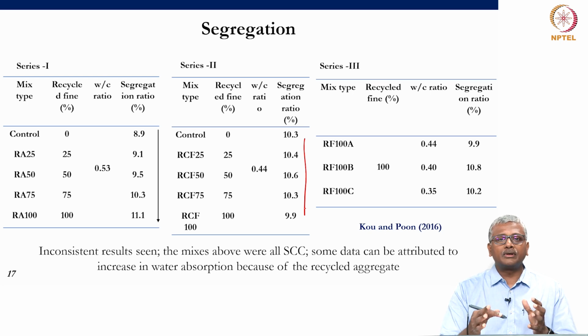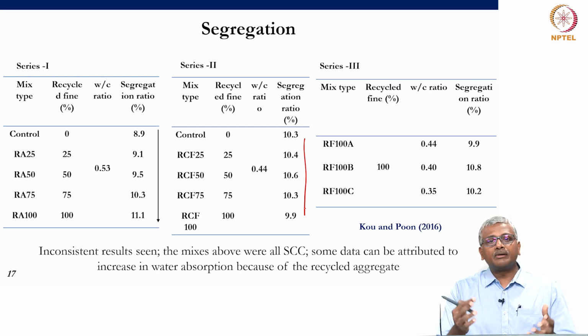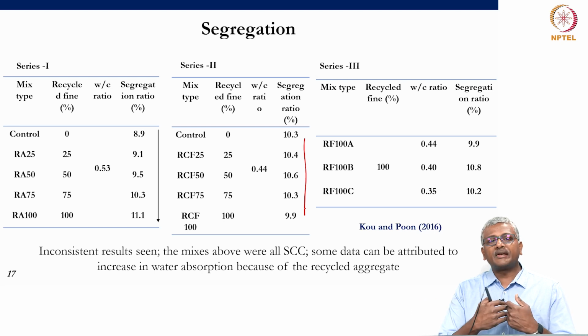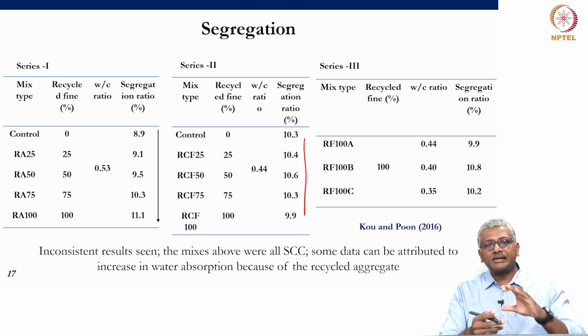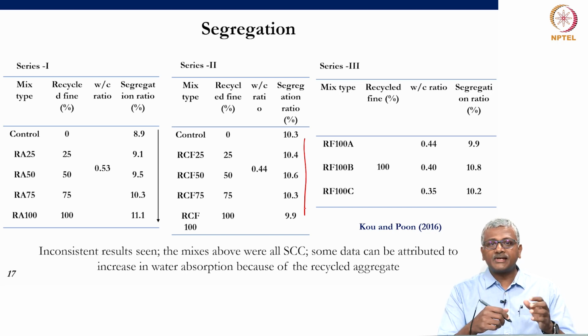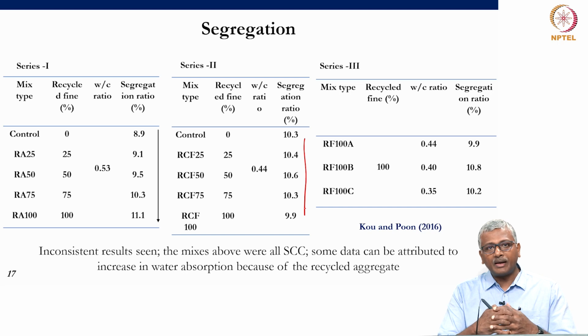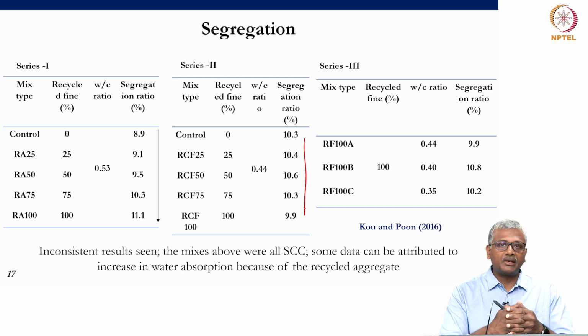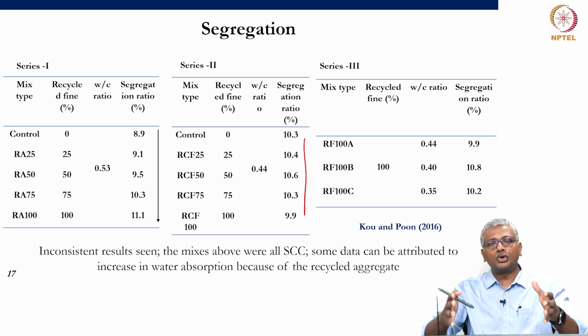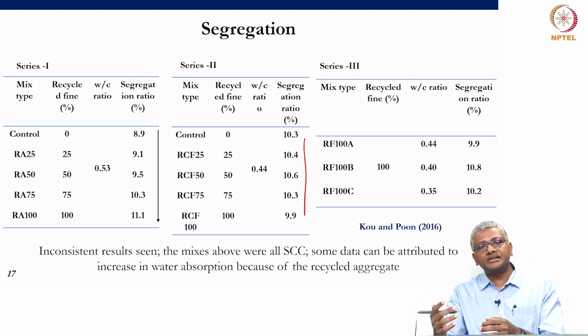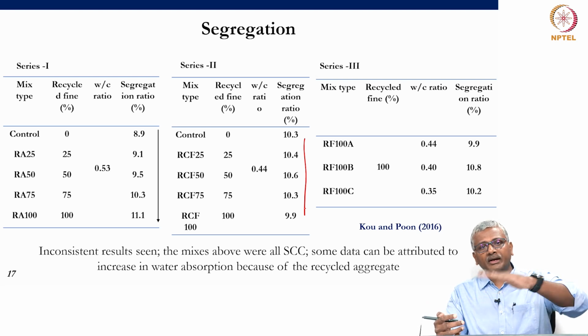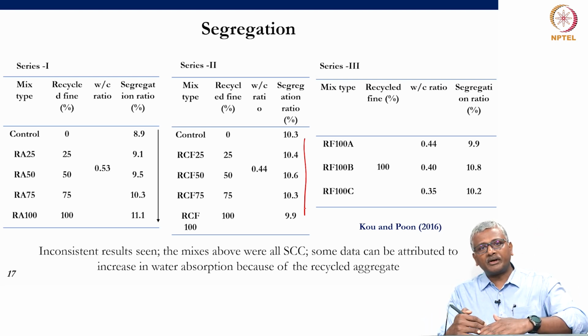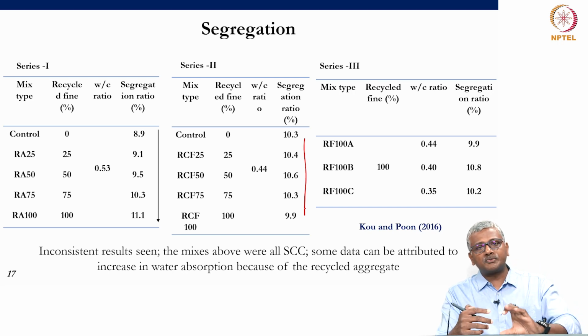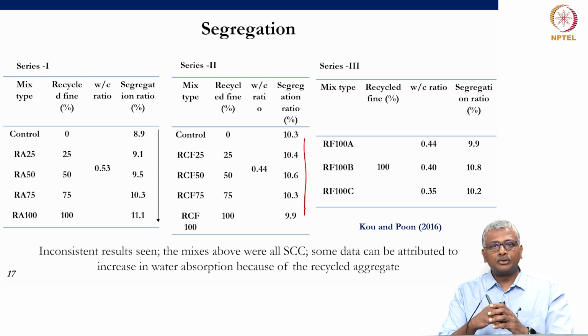Now, just to get you an understanding of what this is. So, in self-compacting concrete, because of the extreme flowability, there is a tendency for the aggregates to settle or segregate as compared to the paste, right. If you do not design your concrete well, that is likely to happen because of the extremely flowable nature of the material. So, in segregation test, what is typically done is the fresh concrete is poured into a bucket. You then wait for 15 minutes, then separate the top 1/3 of the bucket and bottom part of the bucket and determine the extent of aggregate that is present in the two locations.